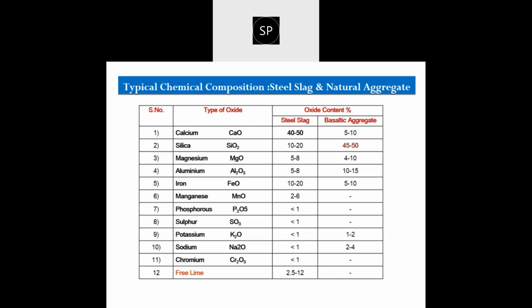Since in this particular process only hot metal is utilized, and in the hot metal, in order to reduce the quantity of impurities and carbon, we have to put a good amount of fluxing agent, particularly dolomite lime, inside the furnace. This dolomite lime goes along with the slag and remains entrapped inside the slag in a free form. So when this lime comes into contact with moisture, it causes volumetric expansion, and this expansion can be between 5 to 12%. If this sort of aggregate is not treated, then premature failure can happen in the pavement structure. So therefore, we devised the slag treatment or weathering methodology in order to facilitate the utilization of BOF slag aggregate in road construction.